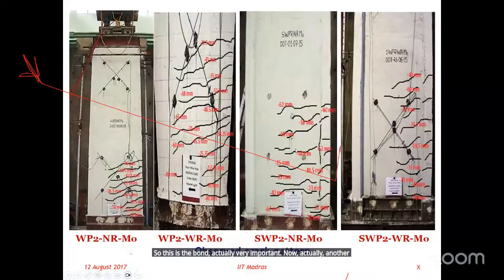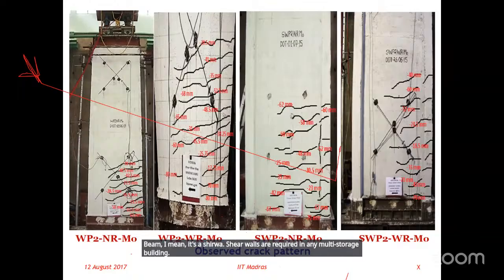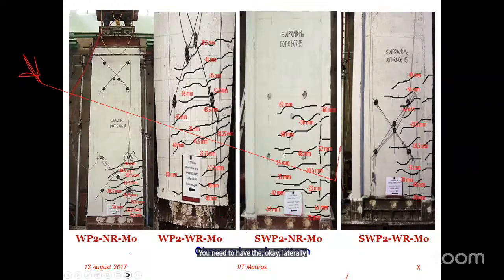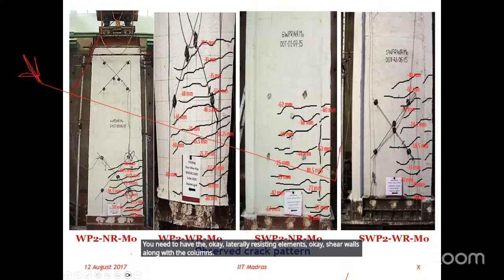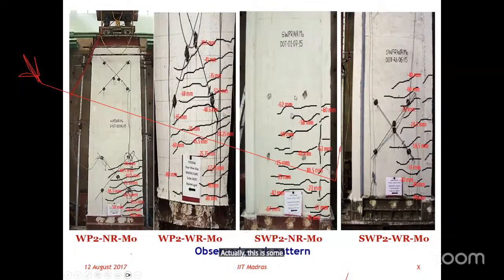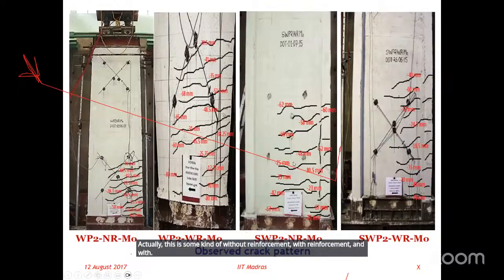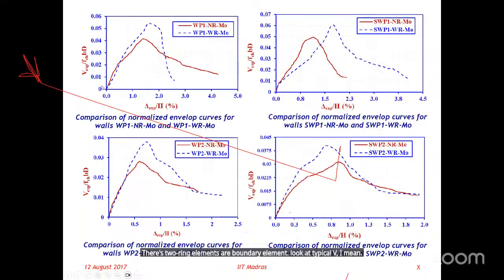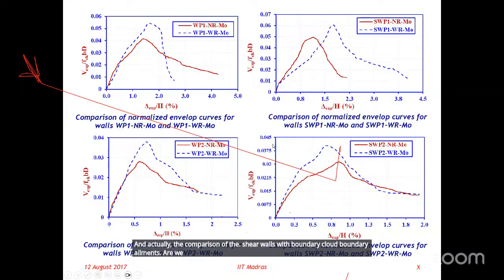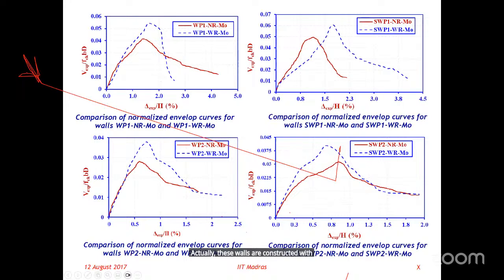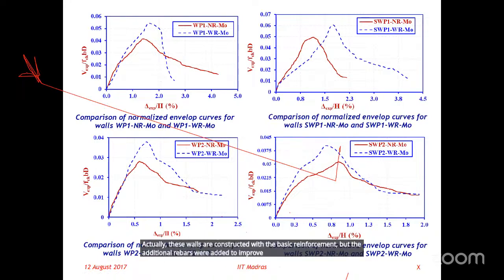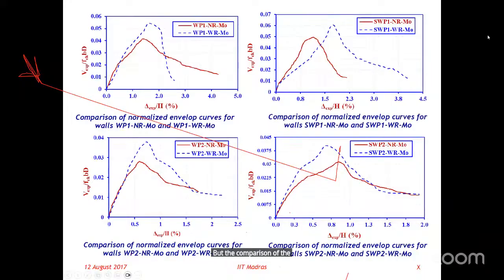Now another important thing is a special element, the shear wall. Shear walls are required in any multi-storied building. Wherever we have ground motions and lateral forces, you need laterally resisting elements, shear walls along with the columns. These are slender walls tested with reinforcement under monotonic and cyclic loading, with or without reinforcement and with stiffening or boundary elements. Typical shear walls were cast, and the comparison is of shear walls with or without boundary elements, and with or without reinforcement. These walls are constructed with basic reinforcement, but additional rebars were added to improve the stiffness or other characteristics, and the comparison is with and without the added reinforcement.